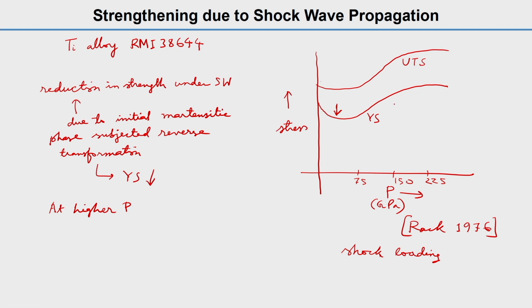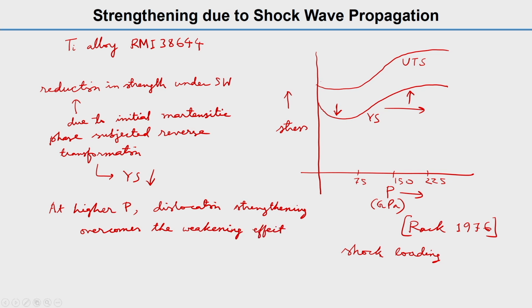But at even higher pressures, in this range, the strength will increase. Why does it increase? Because the dislocation strengthening overcomes the weakening effect due to reverse transformation, the reverse transformation we discussed above. So ultimately the strengthening will happen because dislocation strengthening will be dominant here.